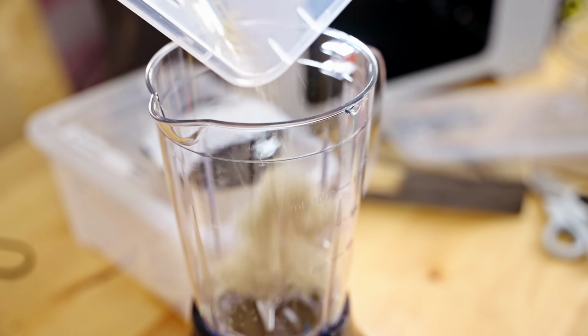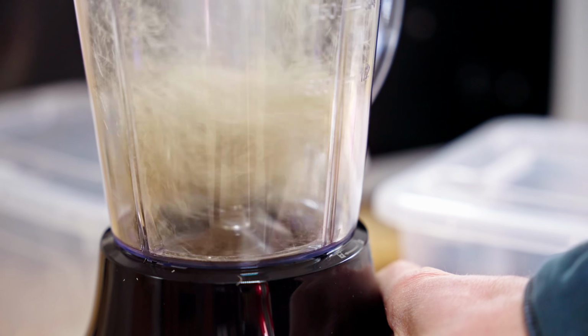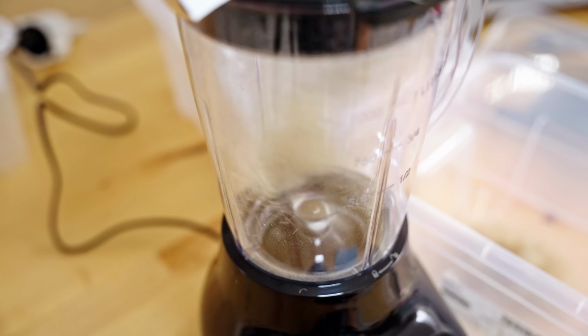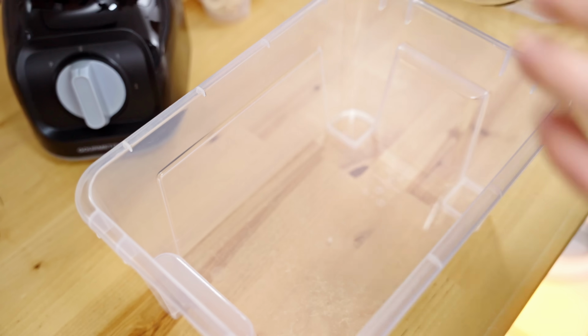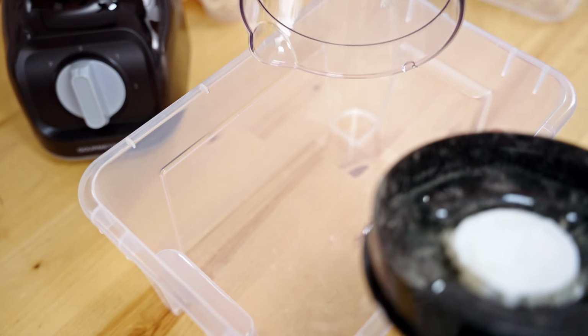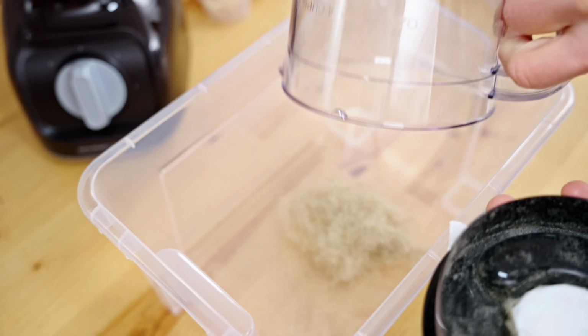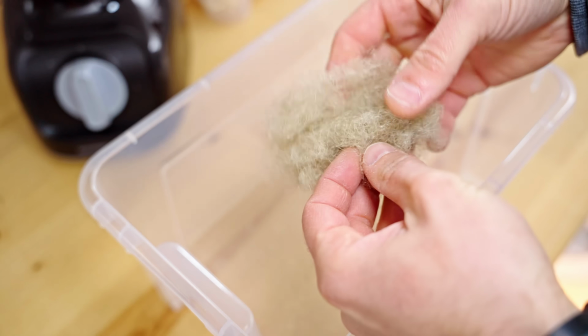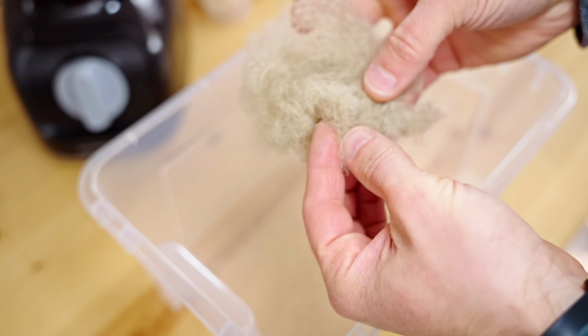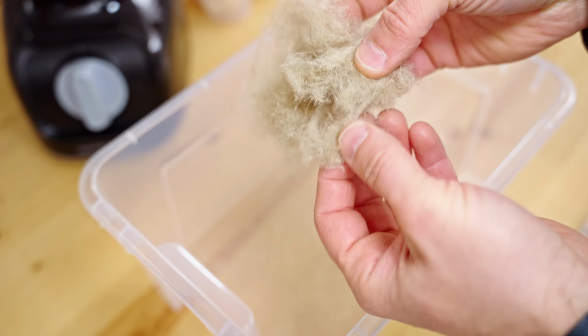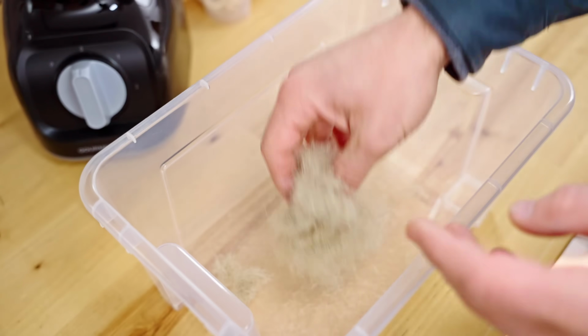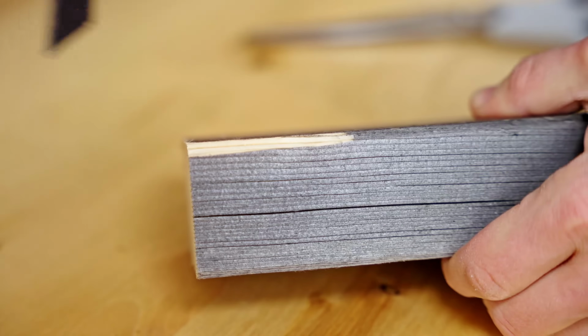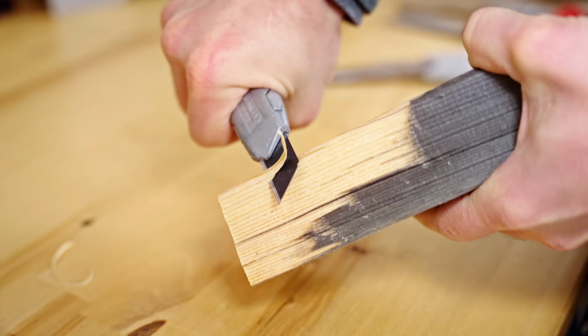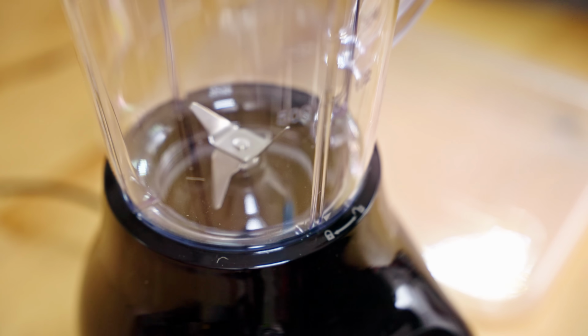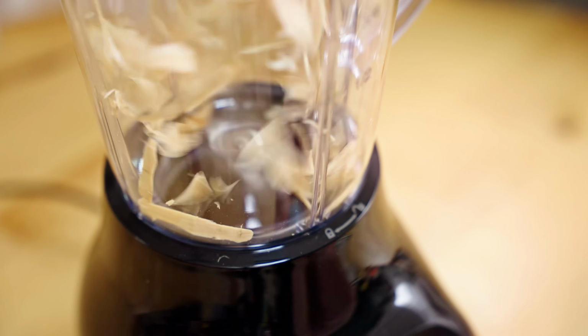Before I had started, I was worrying about whether the blender would be able to chop the fibers, but that actually wasn't a problem at all. As the fibers got smaller and smaller, they also started tangling together more and more, so instead of a fine dust, I was essentially getting a loose piece of felt. And on the inside of that felt, there really wasn't any chopping going on, so these fibers stayed way too long to use. So let's try the wood. Now, wood itself also is a composite material, where you have cellulose fibers being held together by the lignin polymer.